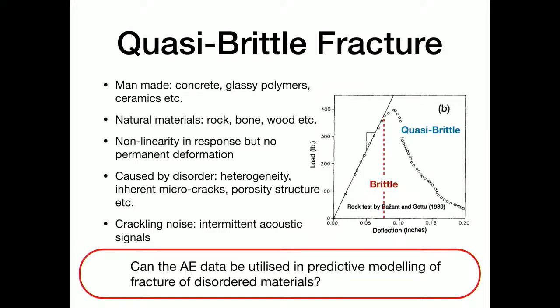That results in nonlinear activity prior to final failure, and this could be due to the presence of microcracks, porosity in the structure, but there is no plastic deformation, as seen in permanent deformation as seen in plasticity. So if at any point in this force deflection curve you unload, you will come back to the zero load situation. So there is no permanent deformation.